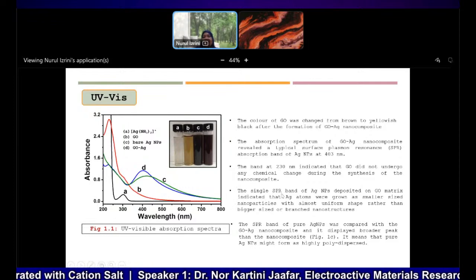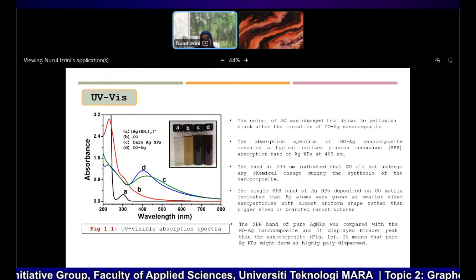Also, the single SPR band of AG nanoparticles deposited on GO matrix indicates that AG atoms grew as smaller size nanoparticles, with almost uniform shape rather than bigger size or branched nanostructures. Because when we don't put any GO, just the AG nanoparticles itself, we see a broader peak. This broader peak means that pure AG nanoparticles might form as highly polydispersed, and that's why maybe they start to agglomerate, not stable. When we add GO, we see a nice sharp peak instead.